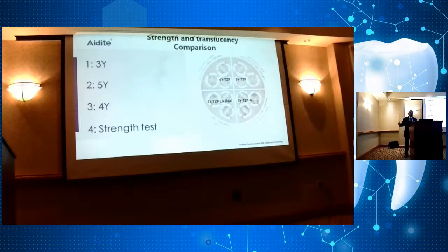So documentation becomes very blurry at times, and they want to always give you the high figure, 650 MPa, 720 MPa. When in fact, if you really do some critical analysis of the material, you'll find that the figures are way below. So I advise my company, Aidite, to always print or publish numbers that are acceptable in the lower range. So if anybody does test it, they'll find that it's actually higher. So 1,050 is our material.